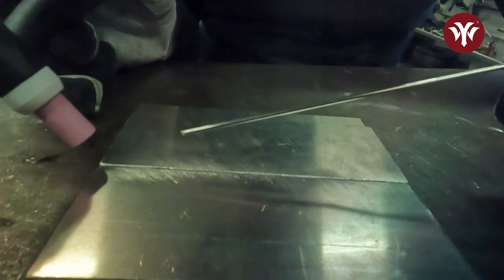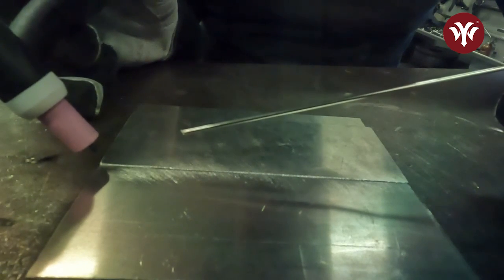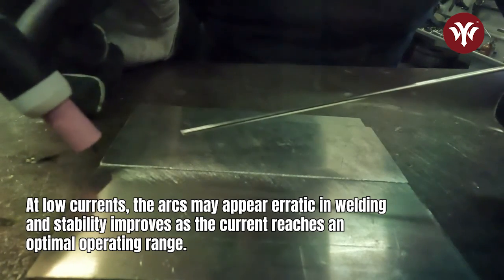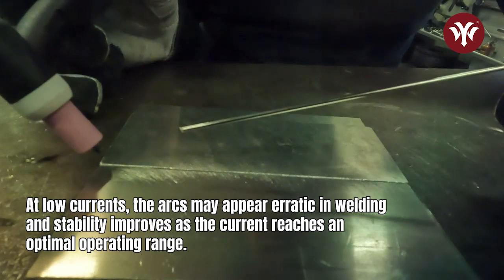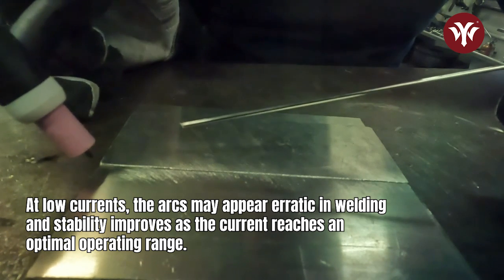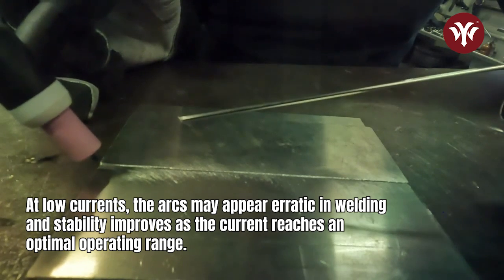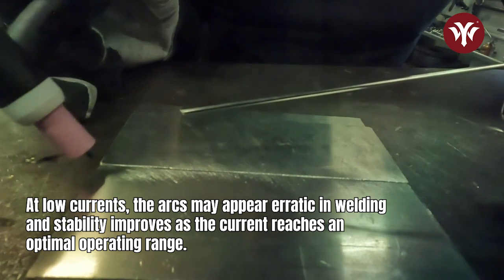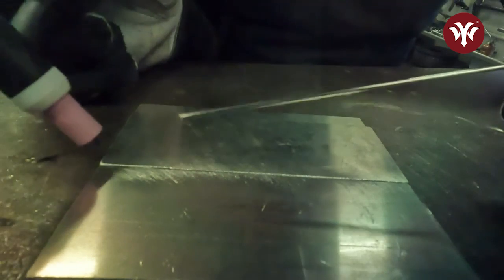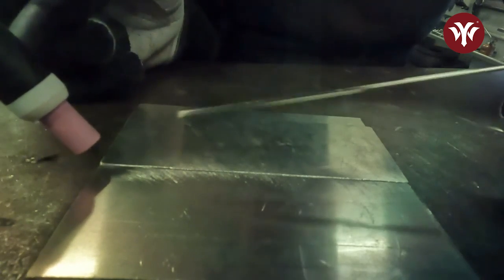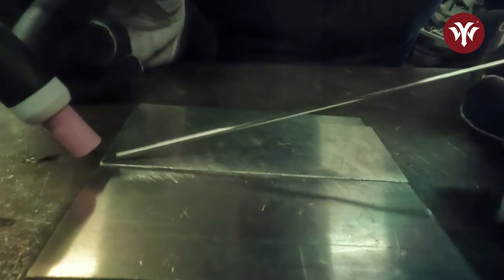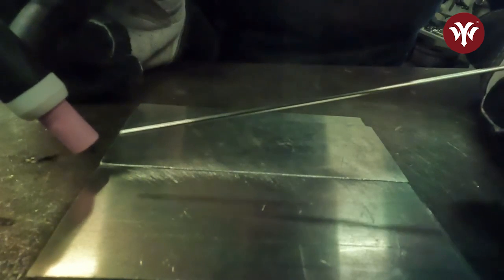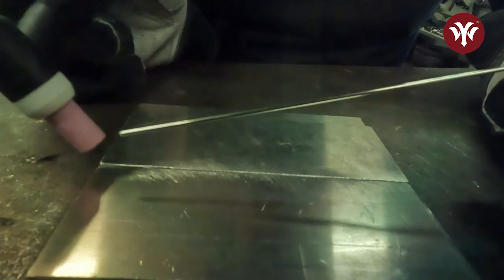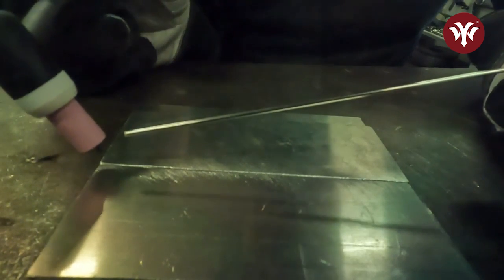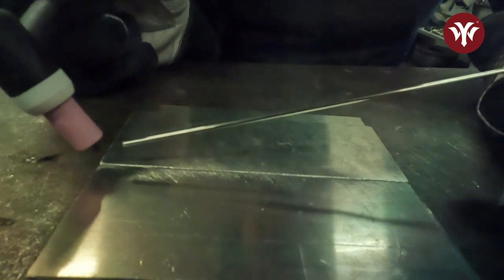We're gonna go ahead, get the arc started. When you're running at low current, you're gonna see the arc's a little bit erratic until you get the current up to a nice operating range, and then your arc will really start to become more stable, and it's gonna wanna go to one side of the part or the other. So we're gonna go ahead, get this arc established, get a puddle established. Sometimes I need to dab a little filler in to help the puddle, but then once we got it there, we're gonna hold that puddle for a second, let the part warm up, and then we're gonna move the puddle along.